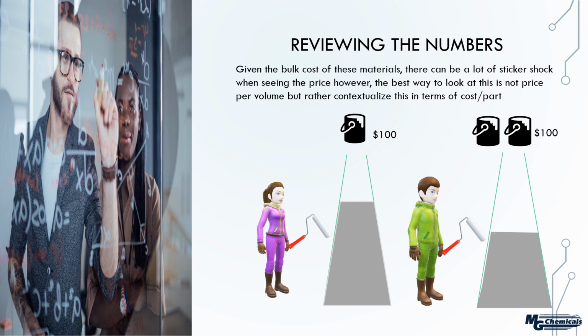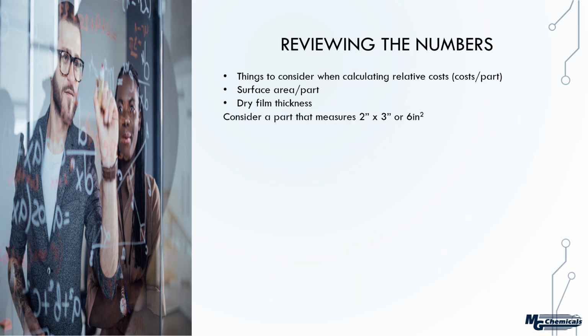So this gives us the same kind of perspective here in that, yes, you could choose a cheaper material, but it may not necessarily save you the money that you think it will, because we have to consider the efficiency of the paint. And here's how we do that. So what we have to consider is getting down to how much each part costs to coat. And to do that, we need to know the surface area of each part and the dry film thickness. Now, the dry film thickness, we give recommended dry film thicknesses, but at the end of the day, a customer is going to have their own process and methods, operator efficiency, that sort of thing. So dry film thickness averages out based on the user more than anything else. And they need to gauge what they expect in terms of dry film thickness.